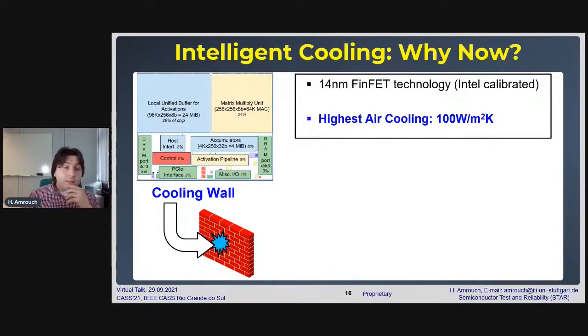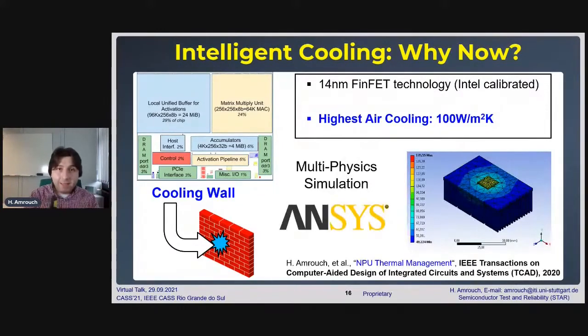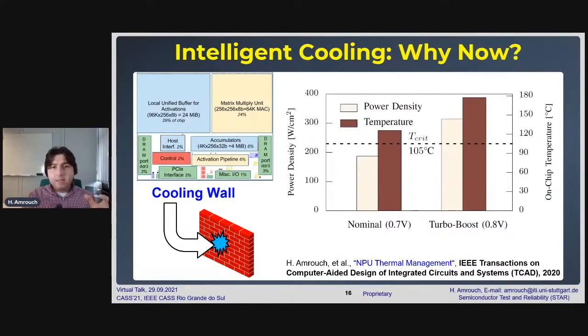In order to investigate this problem, we have done a complex multiphysics simulation using ANSYS, a commercial finite element simulator tool for very advanced heat simulations. We have done that for the entire system, where we have this systolic array mimicking the TPU, and we analyzed the temperature under the maximum and highest air cooling thermal convection. The technology that we used was 14 nanometer FinFET technology calibrated with Intel data.